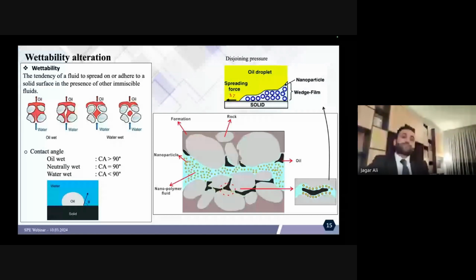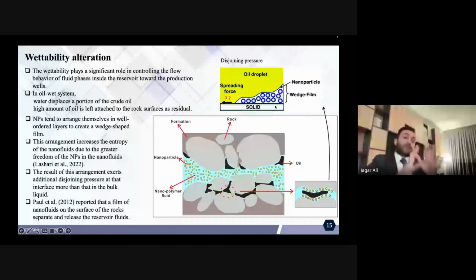For wettability alteration, wettability is the tendency of the fluid to spread or adhere to a solid surface in the presence of other immiscible fluid. So we have this situation inside the porous media. We have rock surface, we have crude oil, and we have water, which are immiscible. They cannot be mixed. So when you have oil wet, the problem is that after injection of water or having water influx, a high amount of crude oil would remain inside the porous media. Usually when we have an oil wet system, it means the contact angle between the oil droplet and the surface of the rock is higher than 90 degrees.